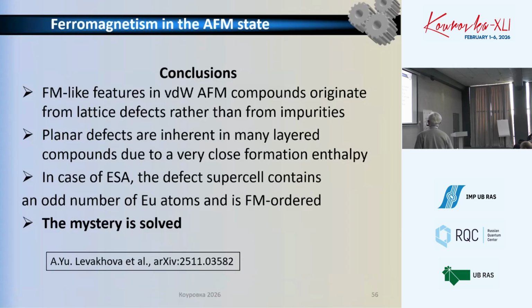And I list here conclusions of this measurement. The ferromagnetic-like features originate not from impurities, but from a lattice defect. You see that the crystal is synthesized and grown at a temperature of about 1000 degrees, and at this temperature it's quite probable that different phases form, which have a thermodynamically close enthalpy of formation. So this is a typical result for all layered compounds, where a planar defect can be easily formed. So planar defects are inherent in many layered compounds due to very close formation enthalpy. And in our case, the defect supercell contains an odd number of europium atoms and is ferromagnetically ordered. So the mystery of ferromagnetic type behavior is solved.